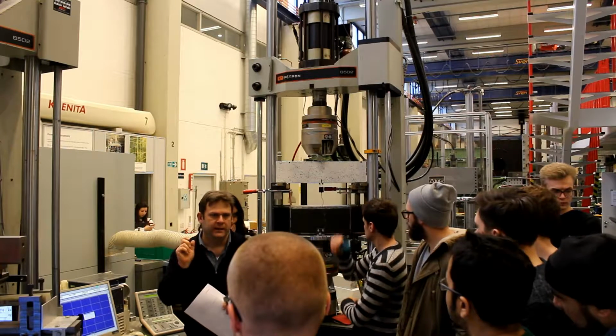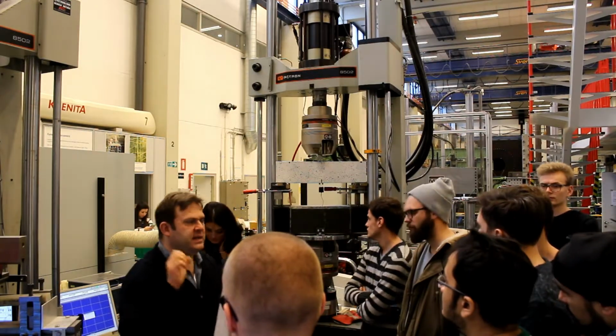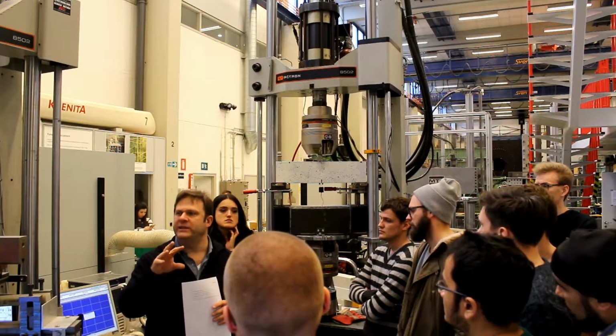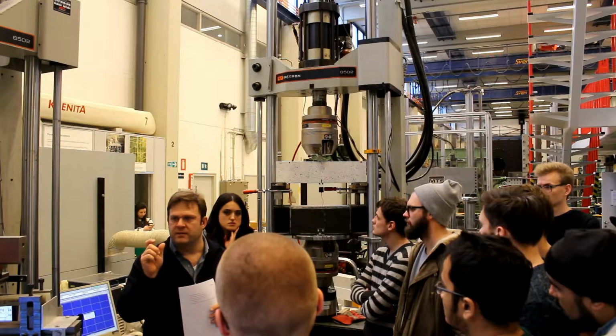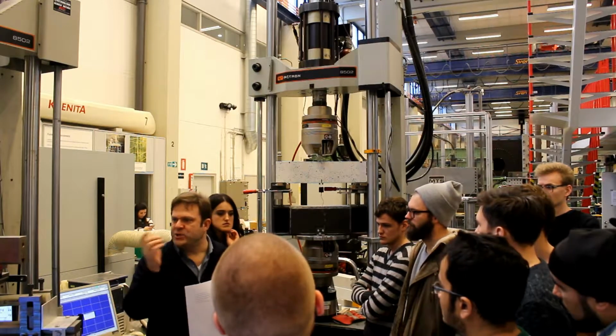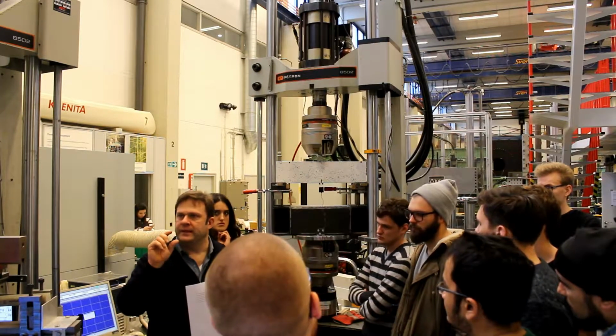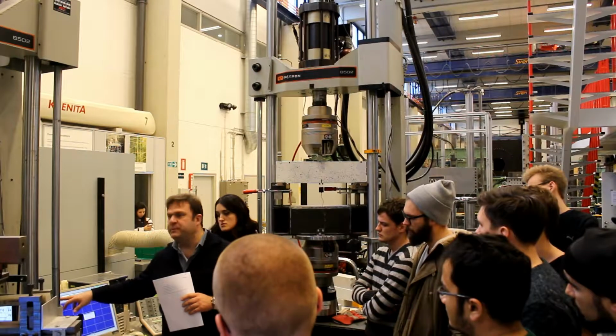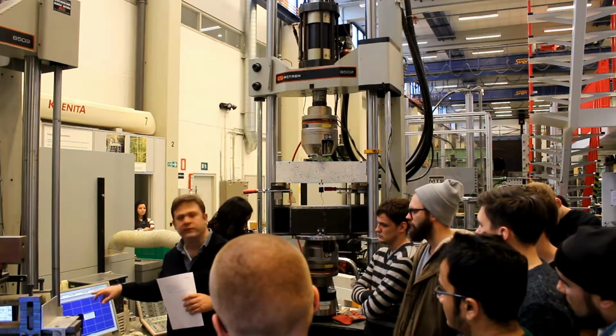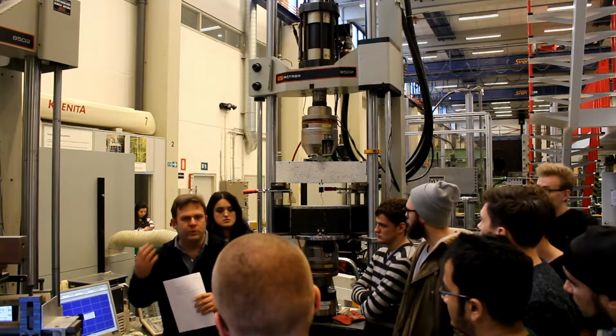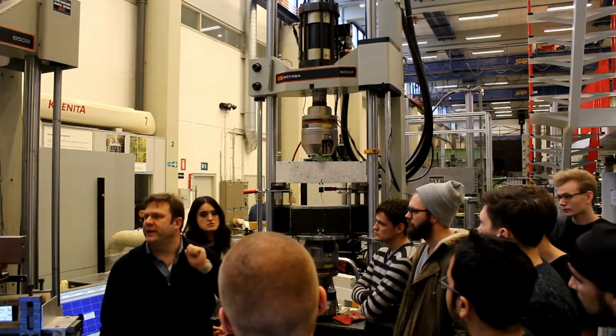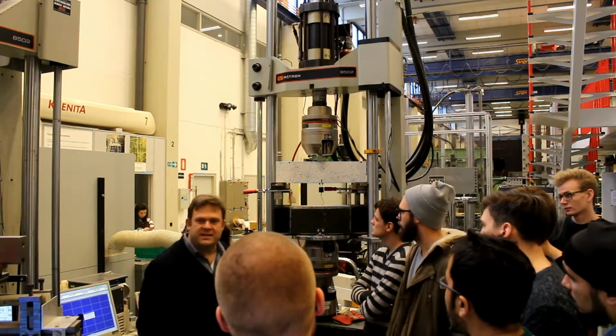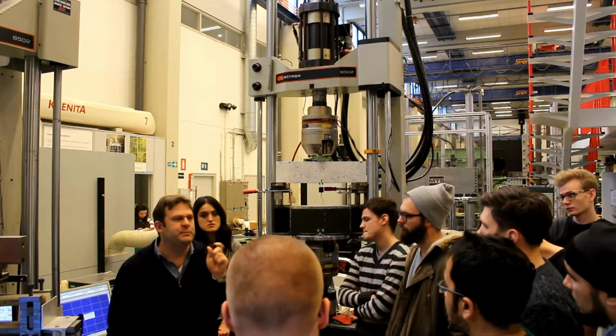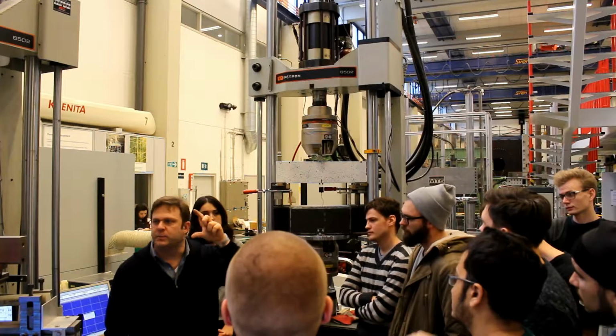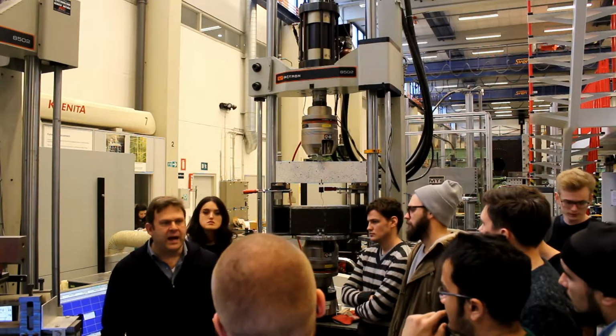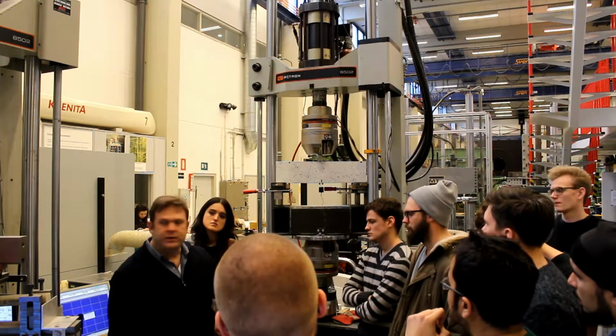The way that the machine does that, it gives us voltage. It does not say anything about kilonewtons right away. It tells us volts, between 0 and 10 volts. And this range between 0 and 10 volts is equivalent to some displacement, some load, and some crack opening. So every time we want to use a new device in a test, we have to calibrate it. We have to say, if the device tells us a change of 1 volt, what does that correspond to in terms of crack opening? Or what does that correspond to in terms of load? So every time that you would normally run a test like that, you would have to do this calibration.